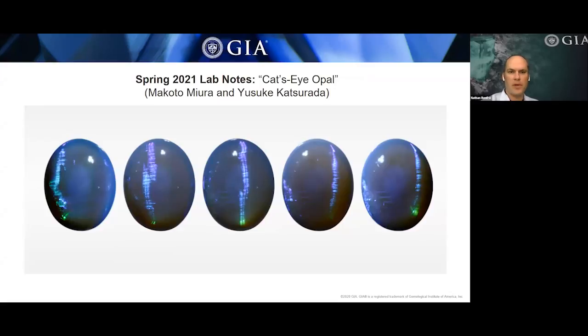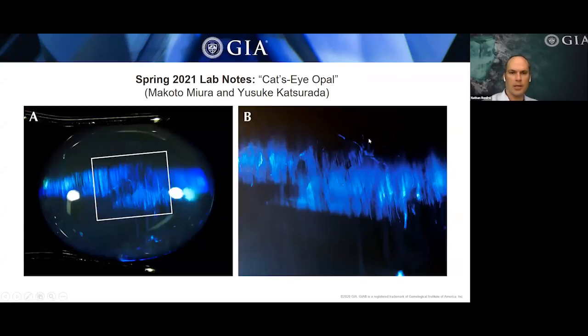Also in the lab notes, there was a Cat's Eye Opal that was written up by our Tokyo staff. Cat's Eye Opals have been previously reported, but they're certainly uncommon. This series of images shows the cat's eye effect rolling across the dome of the cabochon as the light source moves from left to right. Up close in this photomicrograph, we see that the source of the cat's eye is a uniform brushstroke pattern in the play of color. Much like you get a cat's eye effect from needle-like inclusions in, say, chrysoberyl or tiger's eye that produce chatoyancy, the brushstroke pattern is so uniform in this case that you have a similar cat's eye effect because of the cabochon cutting.